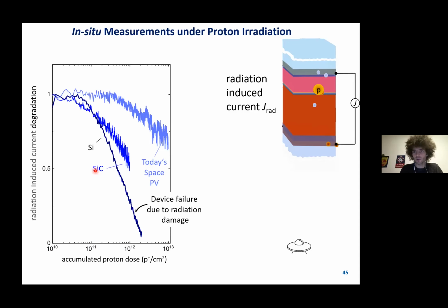So we shoot with protons, excite electrons and holes, which we can measure as a current, and then we can track this current over time to look at the degradation of the device. And I've done this for a bunch of different technologies. So here on the left, I'm now showing the degradation of this radiation-induced current as a function of proton dose for a silicon solar cell, for a silicon carbide diode, but also for a III-V triple junction solar cell as it is used in space today.